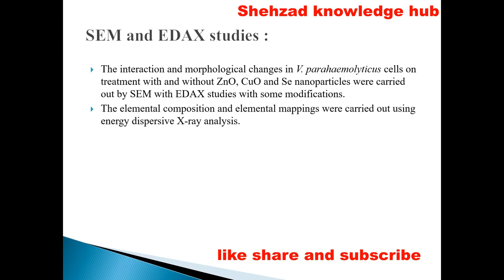SEM and EDAX studies. The interaction and morphological change in Vibrio parahaemolyticus cells on treatment with and without zinc oxide, copper oxide, and selenium nanoparticles were studied by SEM with EDAX studies with some modification. The elemental composition and elemental mappings were carried out using energy dispersive X-ray analysis.